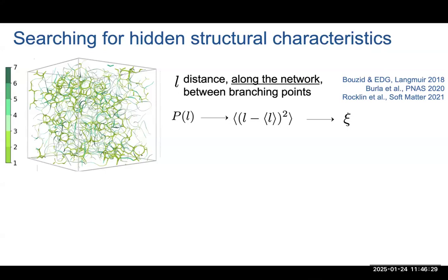We take the shortest one, and this shortest one already has a distribution that is quite wide, and it becomes wider as the gels become more and more dilute, as you may imagine, but also in general as they start to approach the rigidity threshold. So there is a situation in which the gel first starts to become rigid. And at this point, you have the widest possible distribution of these length scales. As your system goes beyond the rigidity threshold, then you get more and more regions that are more tightly connected, and this makes this distribution narrower and narrower.